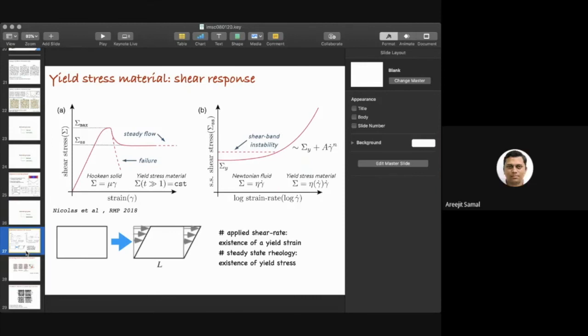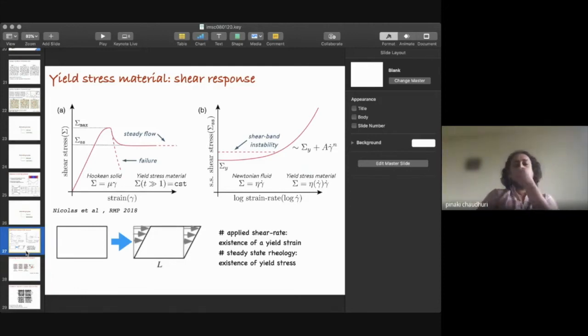Sure, sure. Okay. So if I now take this glass forming system and apply some mechanical stress on the system, for example, I can take this glass, which is, let's say, a cubic box, and then I apply shear. So essentially I'm deforming the system. The standard response of this glass forming system is that you have an initial elastic response, then there is a stress overshoot, then a stress drop, and eventually there is steady flow. This is the typical response of a glass forming system. And this is the stress that is developing in the system as a function of the amount of deformation that the system has undergone.